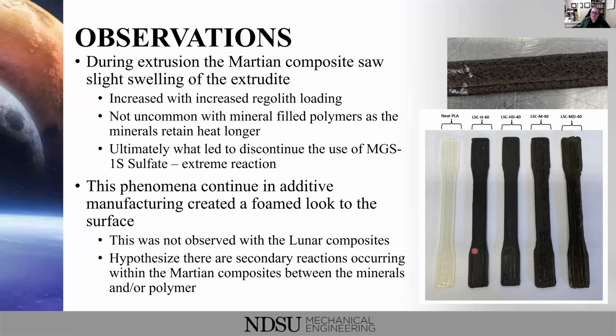So some of the observations, which I think is the more interesting part of this work: we talked about the extrudate, that low melt strength with our sulfate composite. And so we ruled that out in terms of moving on to additive manufacturing during the injection molding. But even the composites that we did additively manufacture, we saw this swelling effect when it came out of the 3D printer. And interestingly enough, as we increased our loadings, that increased as well, right?